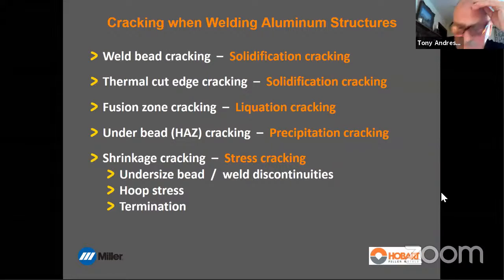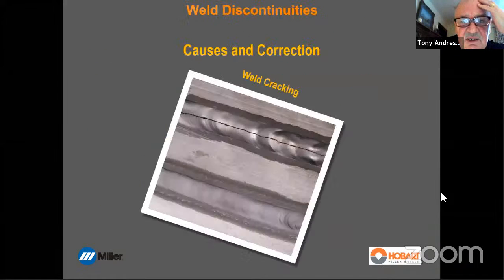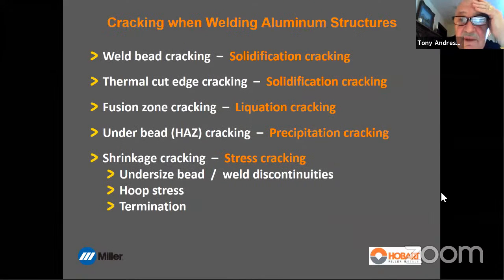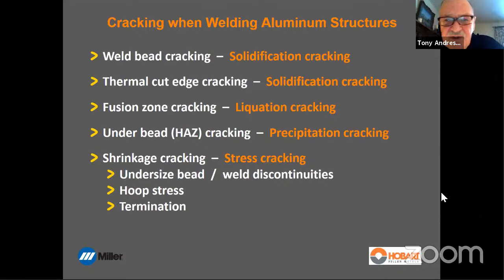All right, cracking. All right, let's go back one. But all cracking in aluminum is hot cracking, and we see it under a lot of different names. Weld bead cracking is often called solidification cracking. Thermal cut edge cracking, I'll talk about, which is also solidification. Fusion zone cracking is often referred to as liquation cracking, and there's precipitation cracking, and we get stress cracking.